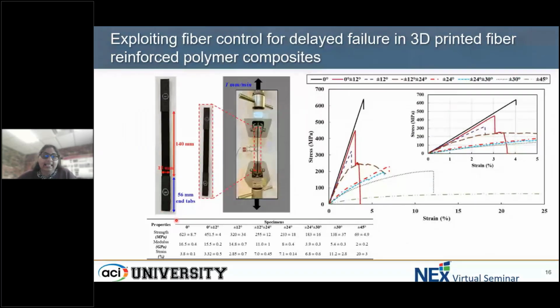So if you look at the project itself that I was talking about, we started off by just printing these orientations like 0 degrees or 12 degrees or 24 degrees because we wanted to achieve their properties. Properties being both the elastic modulus, the tensile strength of the material, as well as the tangential modulus in order to input it into the finite element model. So this is a standard ASTM D3039 test that we performed. By testing all these composites, we were able to achieve a data set of how each of these fiber orientations, and the composites with that particular theta, behave.